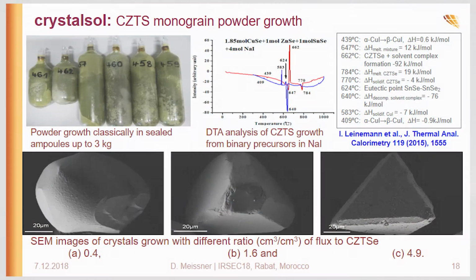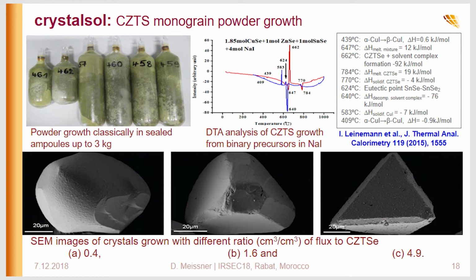So what we do is we grow these crystals by just putting the elements together. We put copper powder, zinc powder, tin powder, sulfur or selenium, or both of them, into an ampoule. We add some salt, which acts as a solvent, because the salt melts. You can see in this differential thermal analysis, you heat this up, nothing happens, and then the red peak, the salt melts, and when the salt melts, you form directly CZTS.